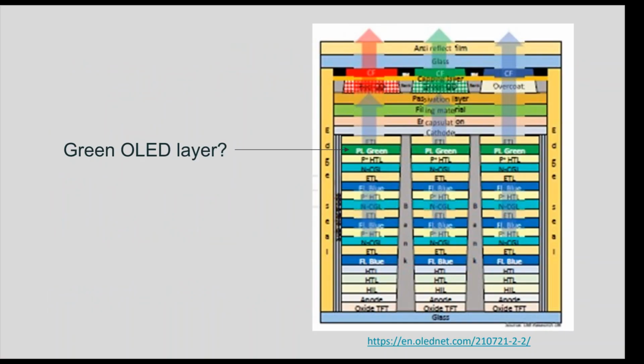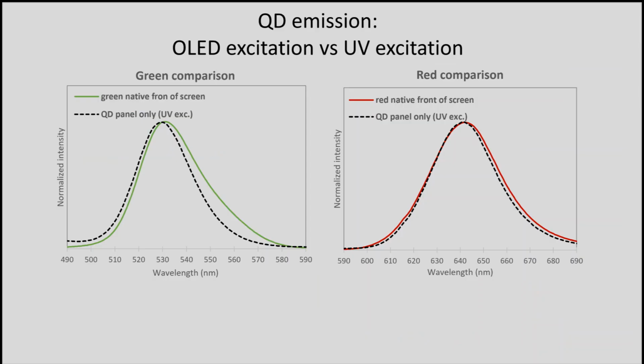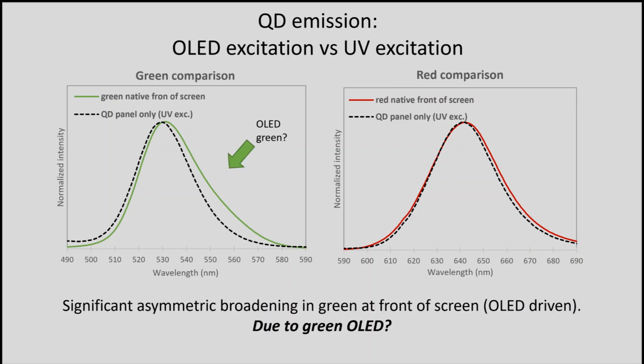I'm not the first one to propose that there might be a green layer here. This is something that's been rumored in this industry. If we look at the green from the front of screen measurement, this is with the OLED backlight, you can see it's a little bit more broad than the QD panel only with UV excitation. In the red case, they're both very similar. So it's possible that this broadened spectrum that I measure at the front of screen is due to the green OLED that's contributing to the color we see in the green.